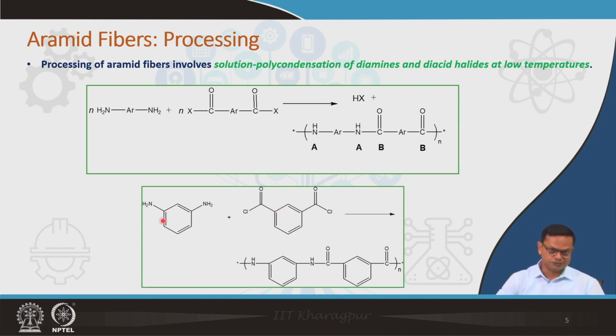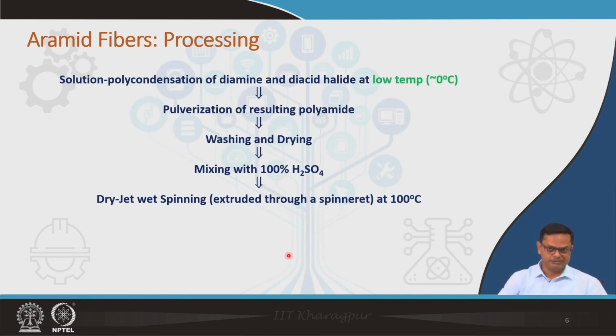So, again let me say it once more, we have diamines and diacid halides, they react, and then you have this NH and then you have this CO, and ultimately those get combined and you get CONH. That is basically the amide group. So, from the amine and the acid halide you get this amide group, which is residing between two aromatic rings. And that is how you get the aramide structure. Okay. So, let us look into the processing in a little bit more detail.